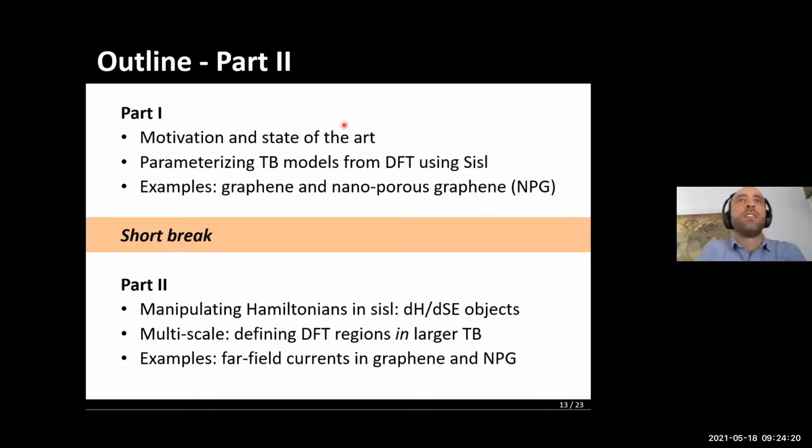So Dongji asks, what is the general strategy to select the targeted orbitals for the projection? For instance, if we want to model some more complex systems than graphene. And the answer to that is what I just said, which is do a fat bands analysis, analyze the orbital contribution to the bands, and see whether the bands you're interested in reproducing have contributions from a limited amount of orbitals. And if yes, then most likely using this command will do what you want.